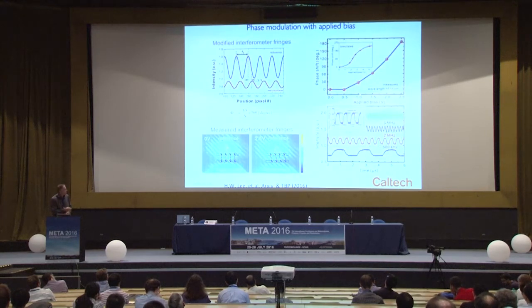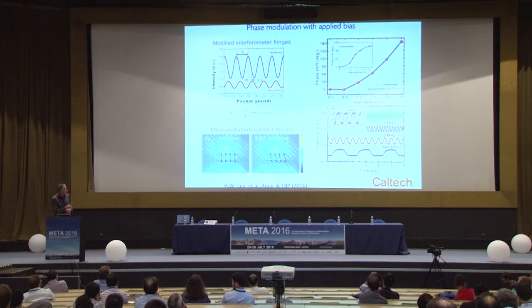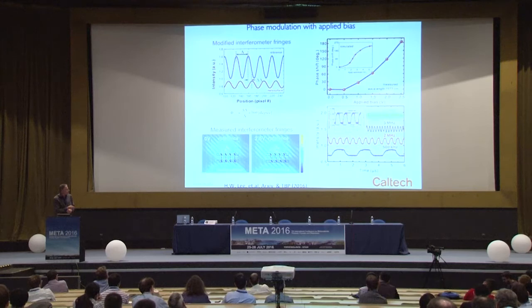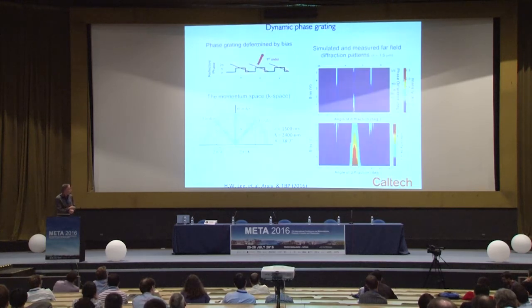But importantly, this also allows us to change the phase. So this allows us to make an electrically tunable phase modulator. As we change the carrier density and permittivity in the conducting oxide, that changes the phase response of the magnetic dipole antenna by about a pi phase shift. We can measure this from a simple measurement using Michelson interferometry. And indeed, this structure, which is very transistor-like in its form factor as a device, operates like a transistor and can operate at quite high frequencies. We have tested the devices up to a few tens of megahertz in our lab, but in principle, these should be operable even at gigahertz frequencies.